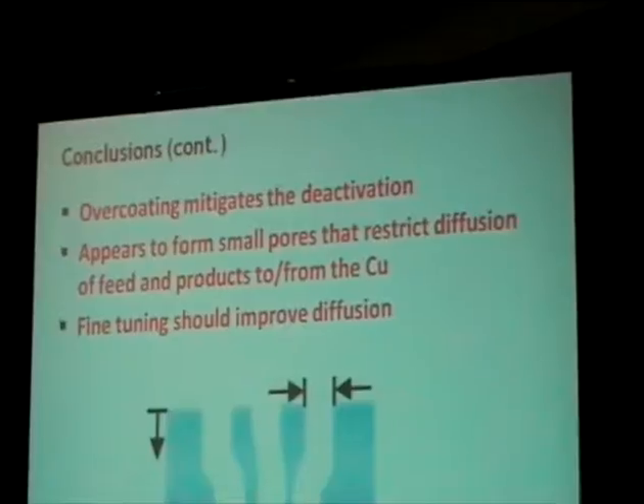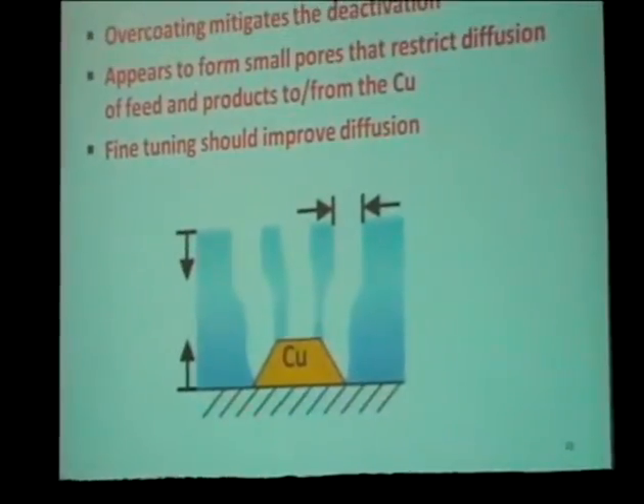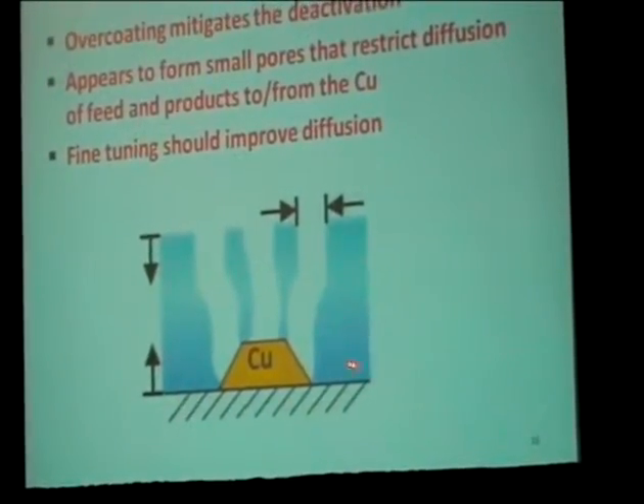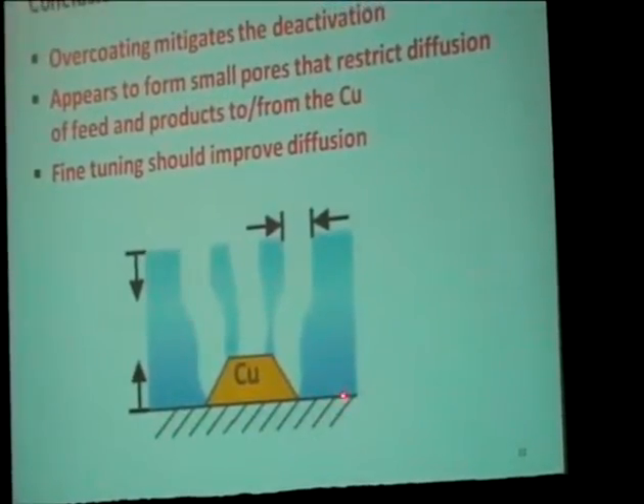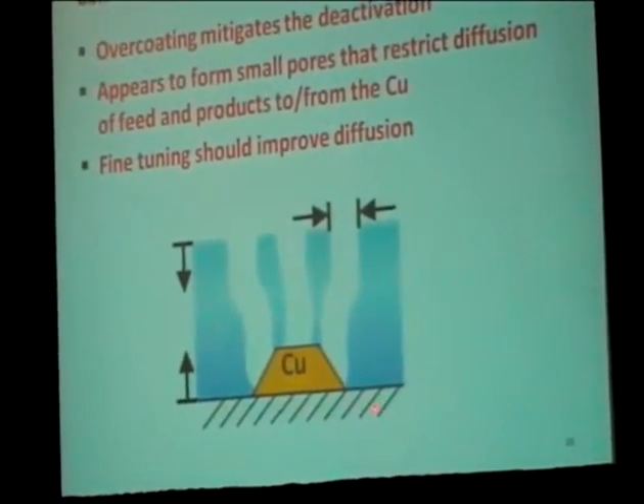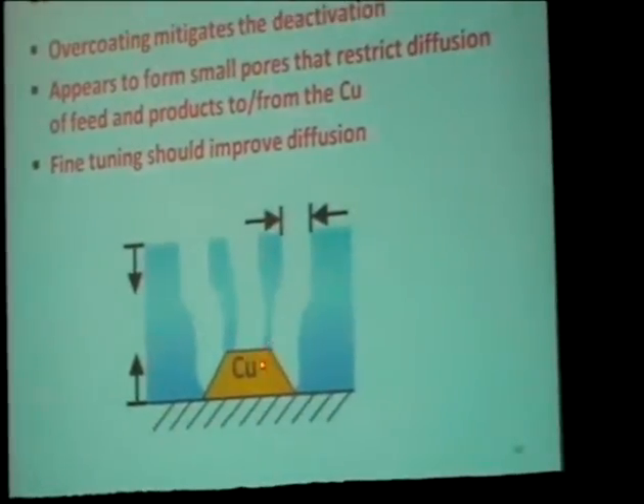The other thing is we found that overcoating the copper chromite catalyst with alumina opens up these pores. We believe right now that the alumina is covering over that chromia, preventing it from attacking the top of the copper here. We believe that these pores that we've generated right now are probably a little too long, so we're looking at changing the amount of alumina that's going onto those materials, and hopefully by changing some of the processes, we can control where that alumina is going onto the surface there.